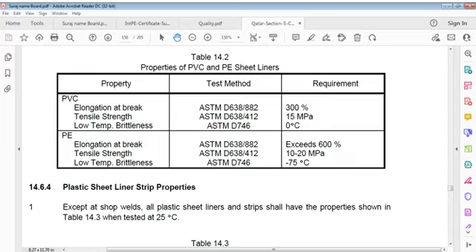Properties of PVC: elongation at break, then tensile strength, and after that low temperature brittleness. According to test method, PVC elongation at break is 300%. You can read the code yourself. 300% requirement, and tensile strength is, I think, 15 MPa. Let me go to the page and see because it is small.